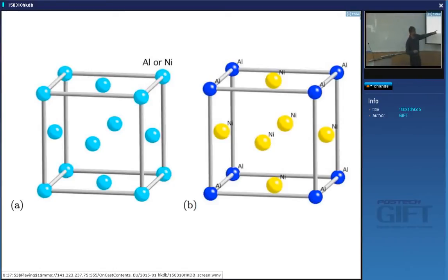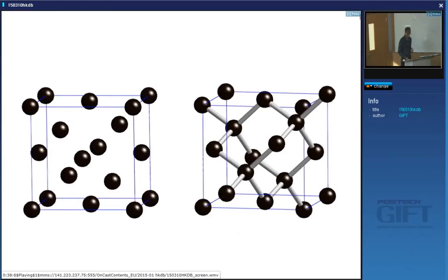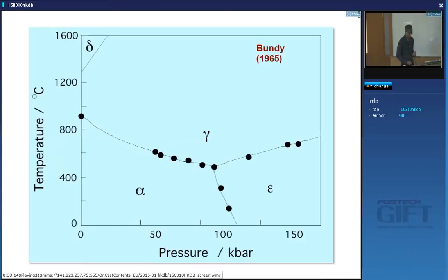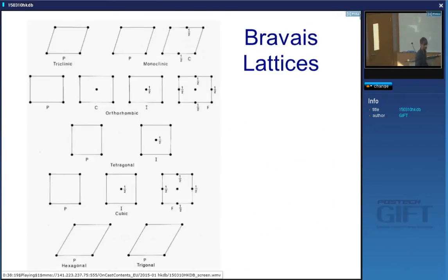Now there is another consequence of the fact that this is cubic P and this is cubic F, right? If I look at the structure projection of cubic F, okay, so cubic F is here. If I'm diffracting X-rays from this layer and this layer, I will not get any intensity because there's a layer in the middle which will scatter X-rays at half a wavelength out of phase. So I will not pick up a 001 reflection with cubic F. I will only pick up 002 planes, half the spacing of 001. If I look at cubic P, there's nothing in the middle.